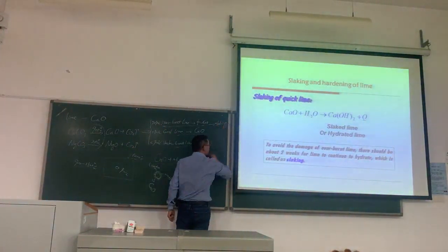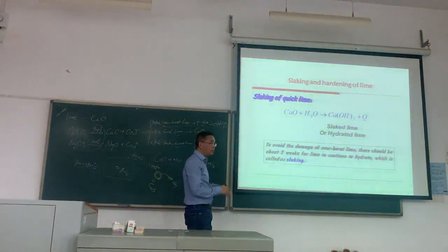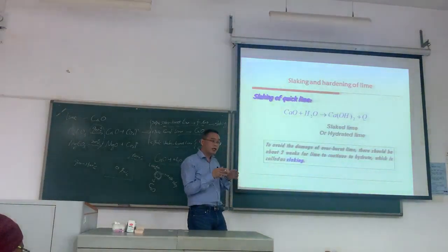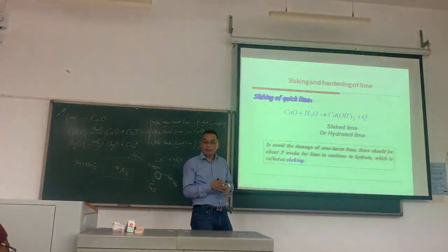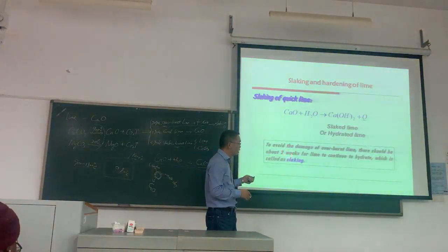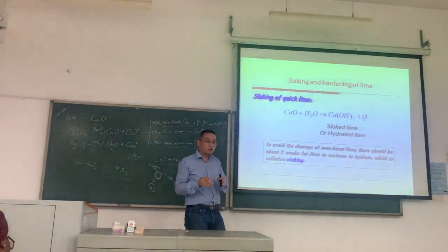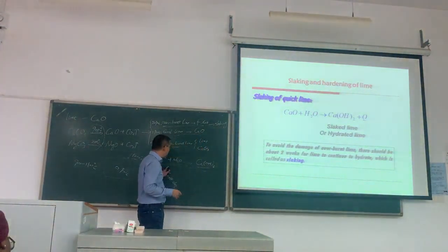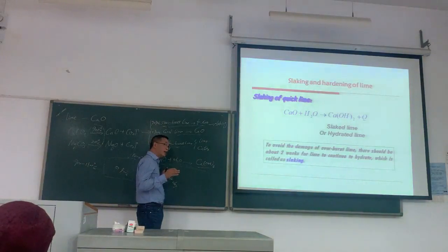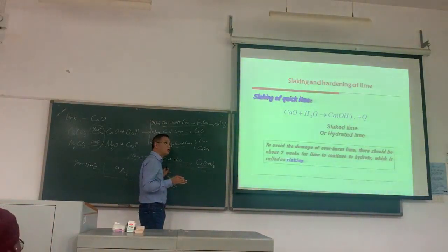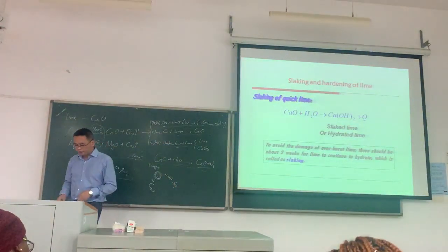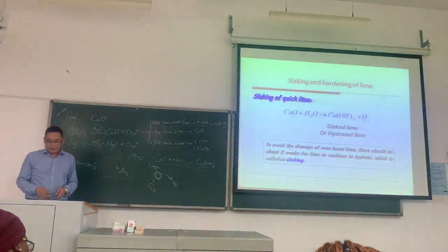What is slaking? It means putting this kind of lime paste aside for 2 weeks. Why 2 weeks? Because the reaction of the overburnt lime is slow, but 2 weeks later, it will react completely. So this is slaking.